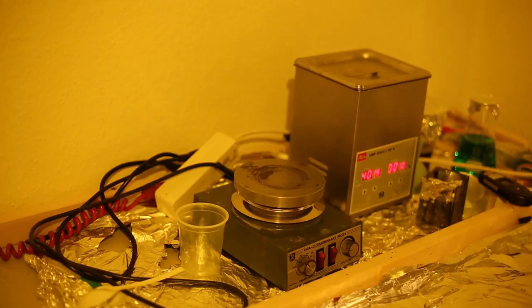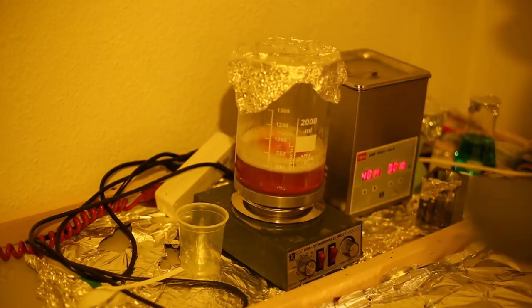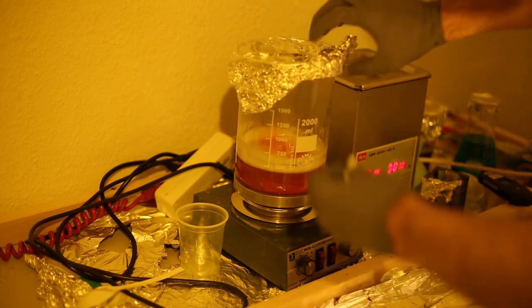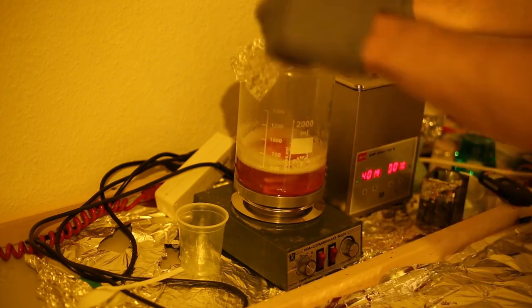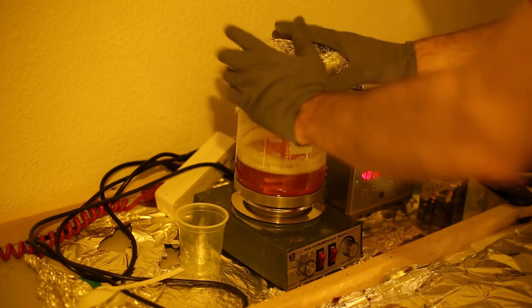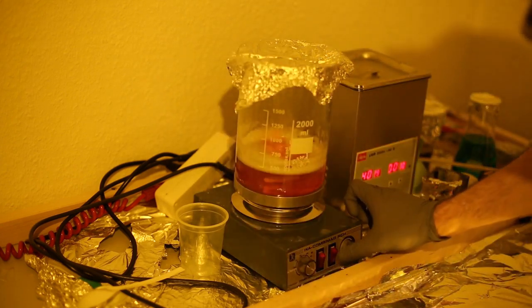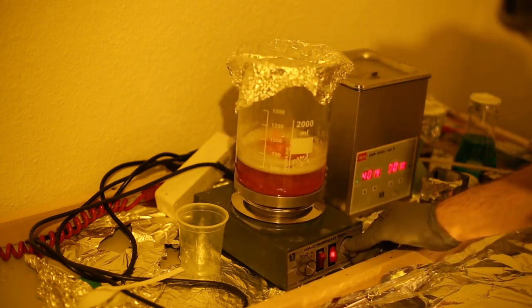I remove the beaker from the glove box and put it onto a magnetic stirrer on low setting and low heating for about 10 minutes. Because the ammonium dichromate is now mixed with the gelatin, it is much safer to handle, because the particles are less likely to get into the air. The next step is to filter the gelatin.